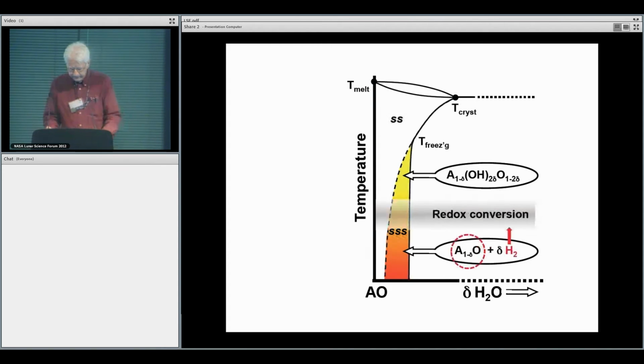Next slide shows that if the hydrogen goes away, you end up with a mineral composition which no longer has any trace of hydrogen, and it is a non-stoichiometric compound. Most of the basic work was done with magnesium oxide as a model, but then it was confirmed for both olivine and feldspars and for a number of other minerals. You have a composition that is an excess of cation vacancies compensated by changes of valency in the oxygen sublattice.